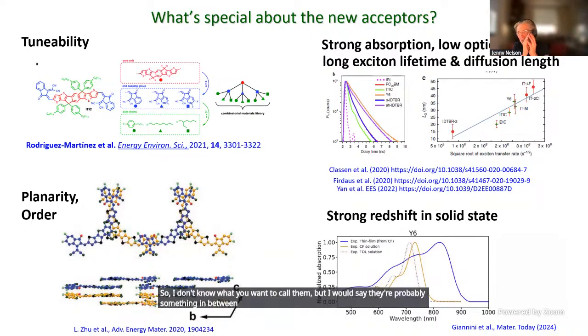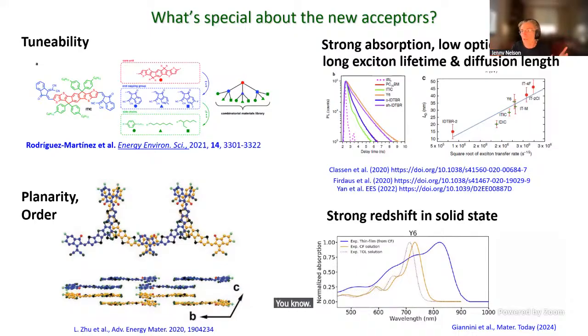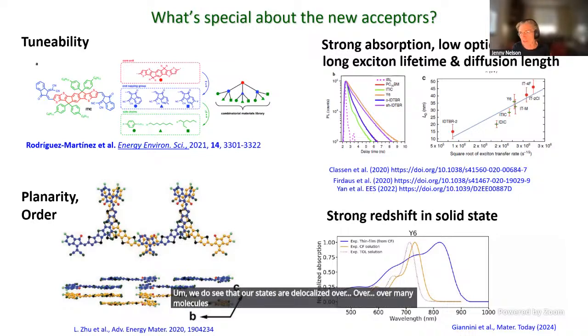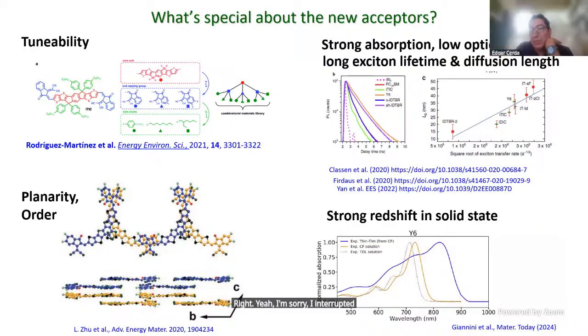They're certainly not the Frenkel exciton as we traditionally think of it, localized on a single molecule, but something which is delocalized. And when we do the calculation of the electronic structure of this sort of mini crystal, we do see that our states are delocalized over many molecules, over several molecules. Right. I'm sorry, I interrupted you. You were saying about why they don't diffuse.